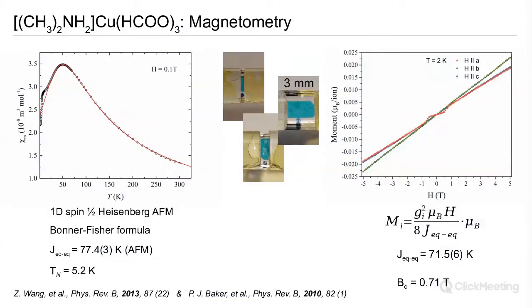So first we did magnetometry, and what we see is much like the case of potassium copper fluoride. We see a broad hump in the magnetic susceptibility. So this is indicative of one-dimensional ordering as we anticipated. But there is a low temperature phase transition at 5.2 Kelvin. We can fit the so-called Bonner-Fisher model for a 1D spin-half Heisenberg antiferromagnet, and we can extract a value for the exchange interaction along that chain. We've also done single crystal magnetometry, where we measure essentially the magnetization of the sample as a function of magnetic field.